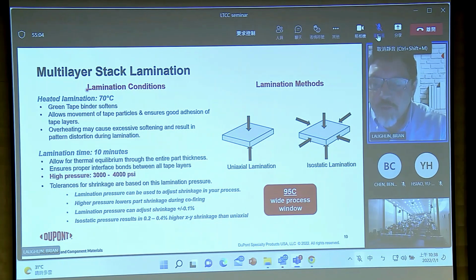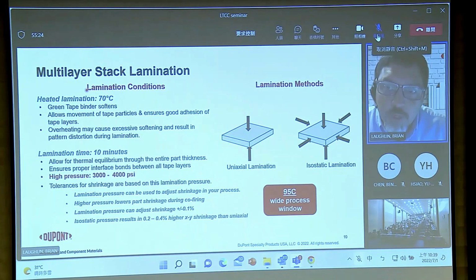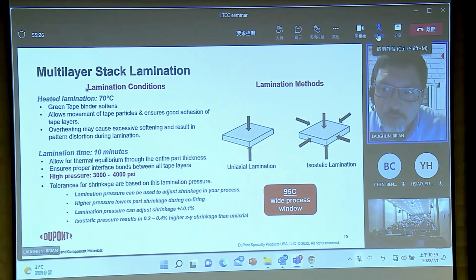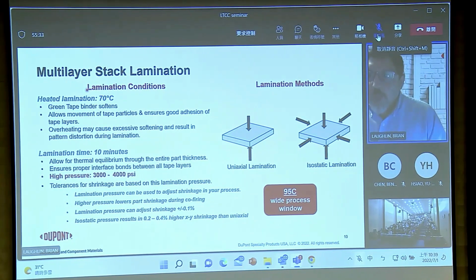So I want to go through some of the important steps of LTCC because they have an implication for your success of making a build. So after you do all of your via punching and via filling and screen printing, and you collate all of your layers together, the lamination is an important step. Because of the way we cast the film, there's a machine direction and transverse direction. And you need to take care to not only collate your parts, but to make sure you alternately assign the different directions of the machine direction and transverse direction.